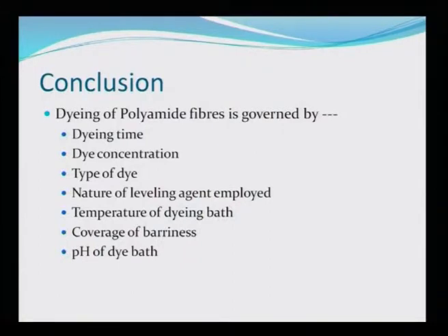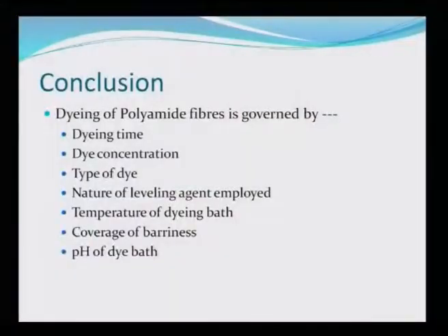Again, the nature of leveling agent employed, because it is the leveling agent which is the surfactant which actually, you know, keeps them together. If this leveling agent does not participate, then the dye dissolution will be a problem, the initial protonation of the amino group in the case of acid dyes, and so on and so forth, will not take place, and the barriness will enhance. So, therefore, it keeps the barriness or the coverage of the barriness lower. Nature of leveling agent is therefore very important, whether it is anionic or cationic, depending on which dye is being used. First thing is the choice of dye, and accordingly the choice of the leveling agent will follow.